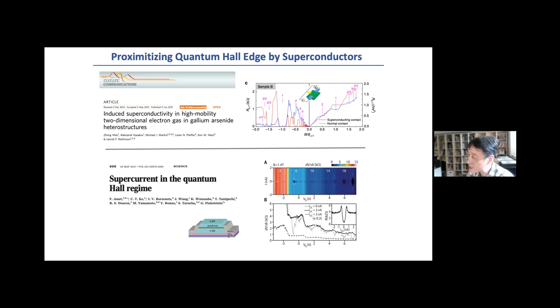However, this is not precisely coexistence, in a sense. By definition, having a Josephson effect means you need zero resistance. In a two-terminal quantum Hall measurement, you always have a quantum Hall plateau. So what they see is that in the middle of the quantum Hall plateau, sometimes the resistance dips to zero to show the Josephson effect. So there is an alternation of the quantum Hall physics and the Josephson effect, but it's not necessarily a truly coexisting case. But this brings us to some interesting directions we can look for.